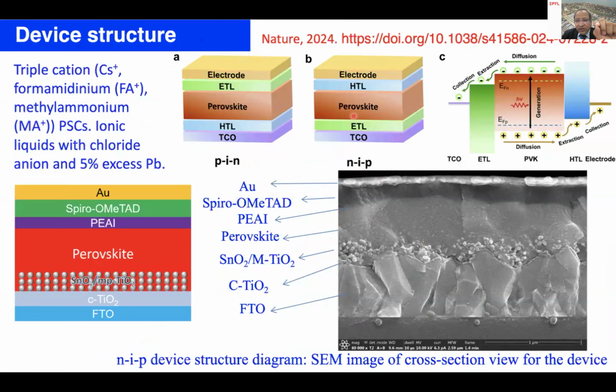The NIP device configuration has light passing through the electron transport material, followed by it hitting the perovskite, and on top we have a hole transporting material. Since the light is passing through the ETL layer, the basic condition here is the ETL layer has to be colorless, otherwise it will absorb light, causing parasitic attenuation.